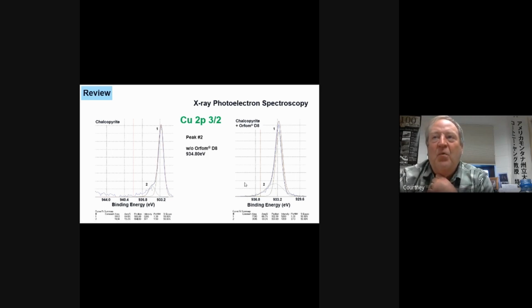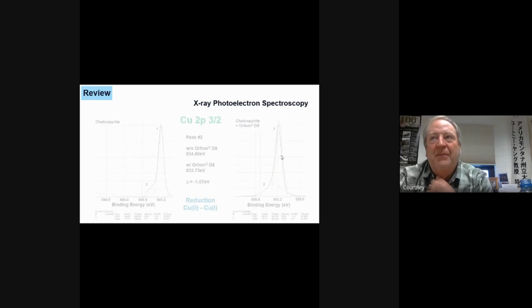And when we look at that without Orfom D8, that peak position is 934.8 electron volts. And it moves to 933.73 electron volts. The difference between those two is negative 1.07, and basically that's telling you that copper is being reduced from copper 2 over here when Orfom D8 is present to copper 1. So we have a reduction reaction that could account for the electrochemistry of the Orfom D8 itself.